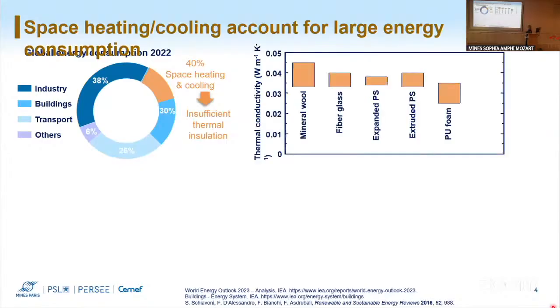The most common insulation materials used have thermal conductivity in the range of 0.03 to 0.04 watt per meter Kelvin. And the lower the thermal conductivity of the material, the better the insulation efficiency that they have. At 0.025, we have the thermal conductivity of air, and all materials that possess lower thermal conductivity are considered to be super insulating. In this area, the only solid materials that we can find are aerogels.